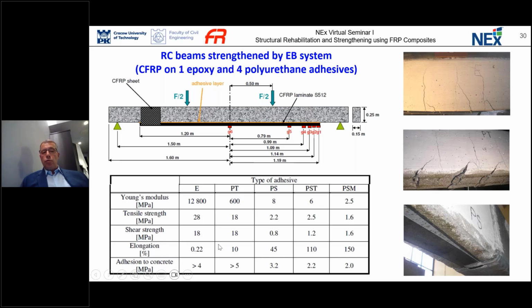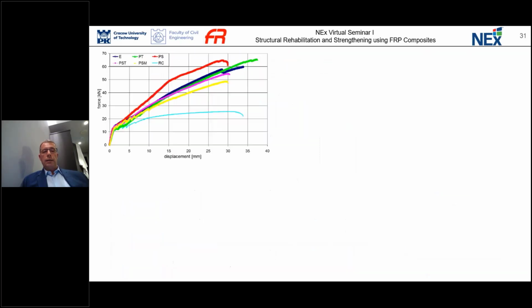On the other hand, you can compare the elongation. We start from 0.22% for epoxy resin up to 150 for PSM type polyurethane flexible adhesive. If we compare on the same scale, on the same graph, the behavior curves of these systems, and compare them with the reinforced concrete reference system, you clearly see that all these systems practically behave in a similar manner.